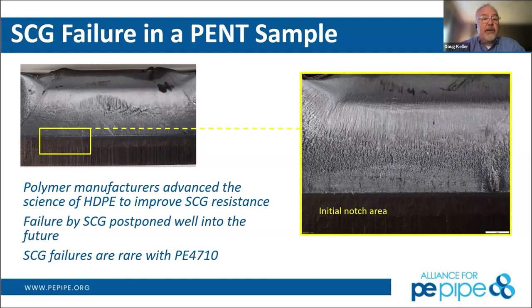4710 materials have to be greater than 500 hours of PENT. Is it linear to say that a material with 500 hours of PENT is 6,500 years plus in the ground? Probably not, but it is well out into the future such that it doesn't become a concern. And most of the 4710 materials today are 2,000 to 10,000 hours of PENT. So really, if the pipe is properly installed, we do not think that slow crack growth is going to be an issue and will cause failure of the pipe well beyond its design service life.